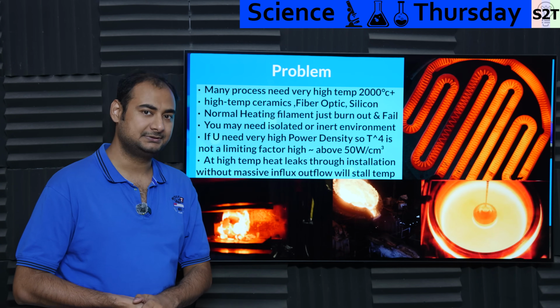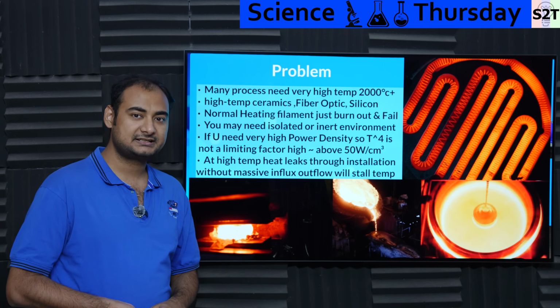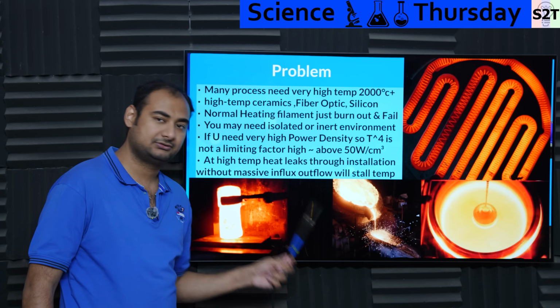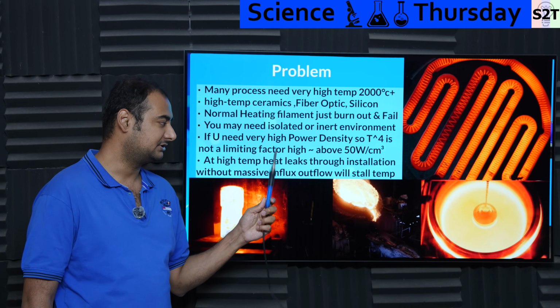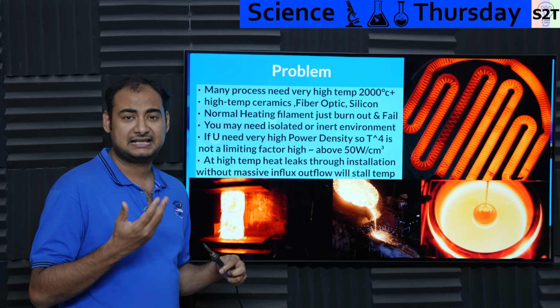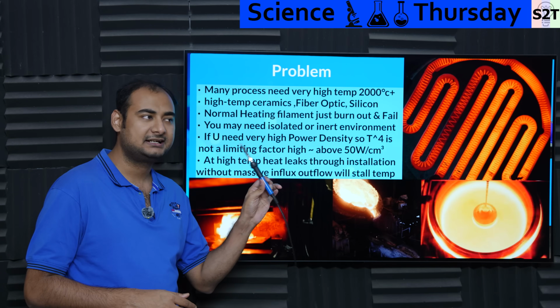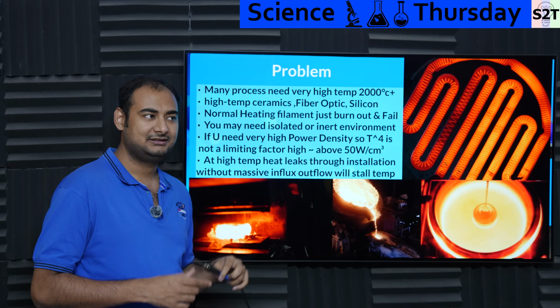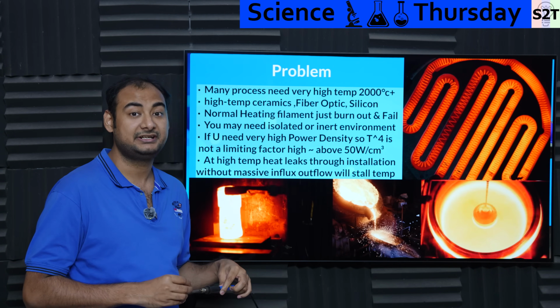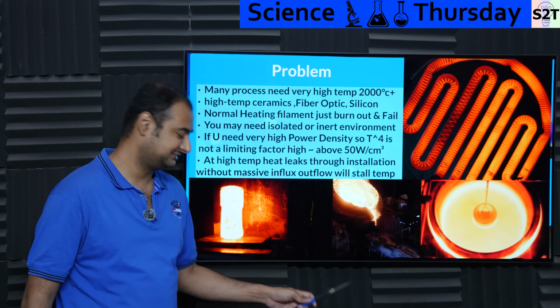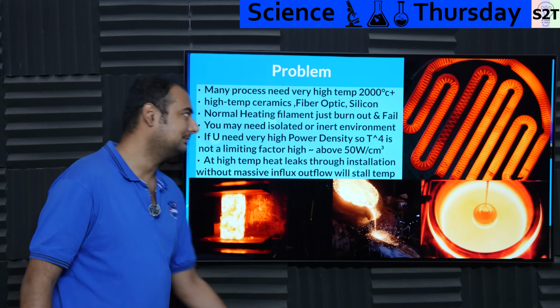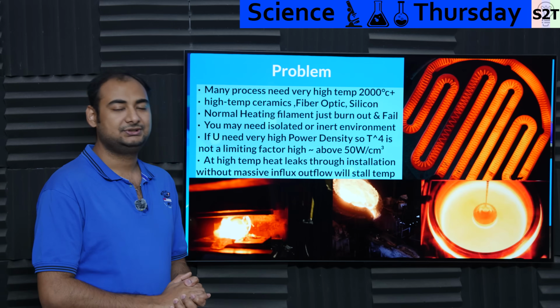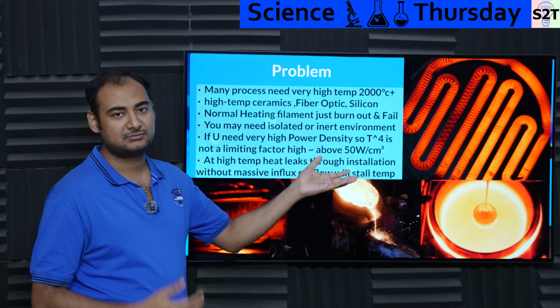simply not heat up. You can notice that in your soldering iron, things of this nature, because if the solder melts at as low as 230 degrees Celsius, why the heck do irons need to go to 400? Well, if they don't go to even as low as 300, it will take too long to melt. Heat will not flow. So fundamentally, you have a fundamental limit with normal heating elements.